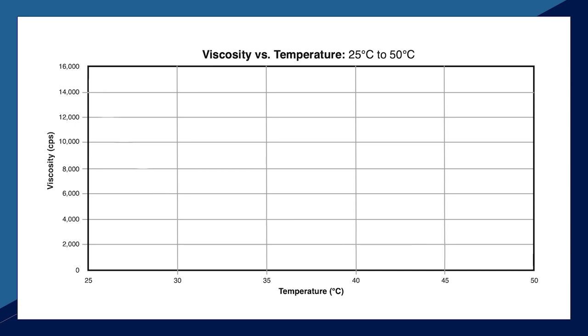Here you will see the viscosity versus temperature curves, which are key in a trickling process. The EPIC ProPreg E240 has a viscosity manufacturing specification range of 13 to 18,000 centipoise, while the polyester acrylate has a viscosity of 2,000 to 2,500 centipoise. Initially, when engineers see the noticeably higher viscosity of the E240, they become concerned with the wickability into the slots and how quickly the resin will absorb into the windings.